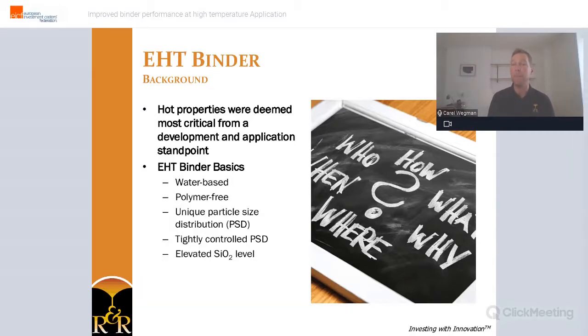It had to be compatible with current flour and stucco materials, preventing dimensional changes. It had to have equal or better green and fired strength to improve dewax performance, equal or better strength at cast temperature, equal or lower strength post-cast to avoid hot or cold tearing and recrystallization, and a minimum 6 month slurry life, but preferably up to 1 year. We deemed that the hot properties were the most critical from a development and application standpoint.